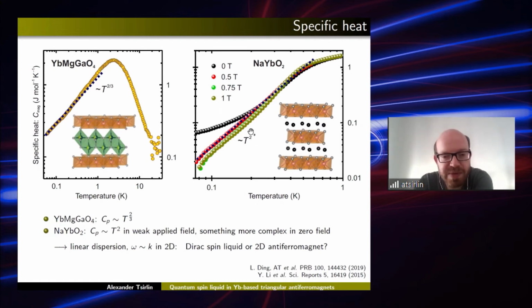So basically, when we see the T-squared behavior, we know that it's a 2-dimensional system with a linear dispersion. So the excitation should be linear in k, and the system should be 2-dimensional. And there are 2 possible explanations for that. One is, let's say, more exotic, that we have the so-called Dirac spin liquid. So the spin liquid with the linear excitations coming out of the Dirac point, just like in the electronic topological materials. And the second, more trivial explanation is that we have the simple 2-dimensional antiferromagnet, we have 2-dimensional spin waves, and they cause the T-squared behavior.